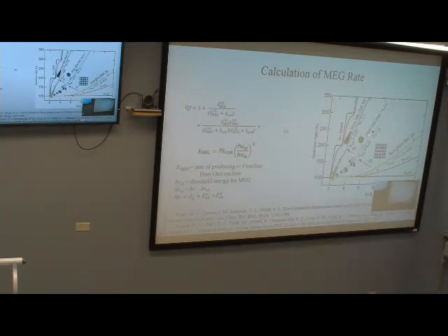And this one is selenium quantum dots. So you get the multi-exciton after exciting at about 2.6 times the band gap. And if you increase P to be very, very large, close to 10,000, you will get this step line. This step line may indicate 100% efficiency of multi-exciton generation. That means if you excite at 2 times the band gap, you will get 2 times multi-exciton generation. Naturally, it's not possible here.